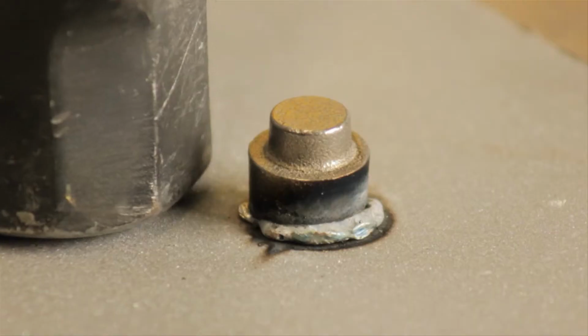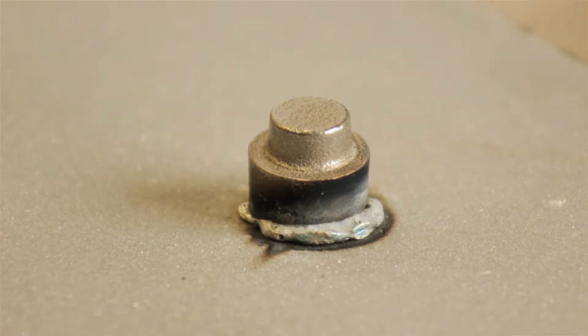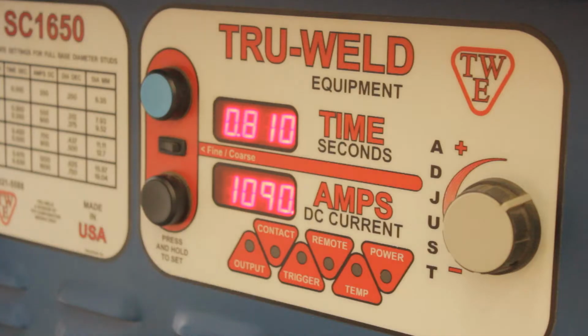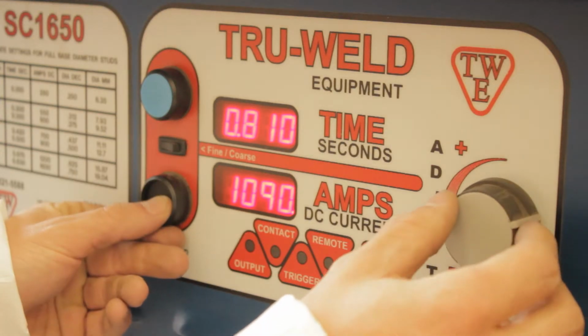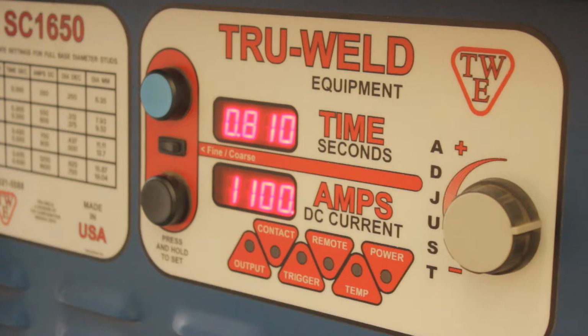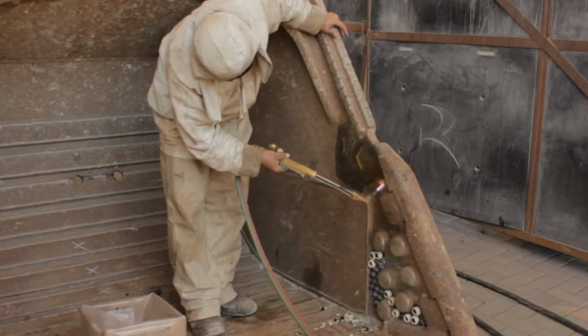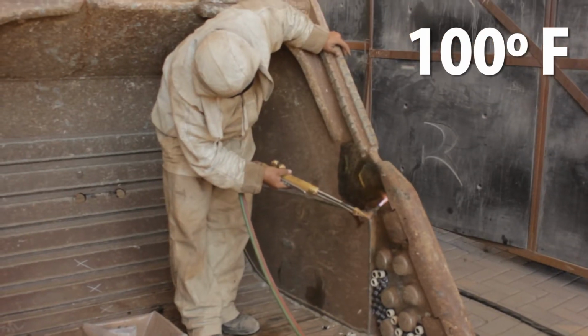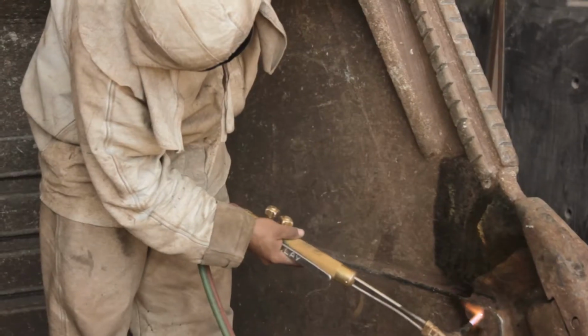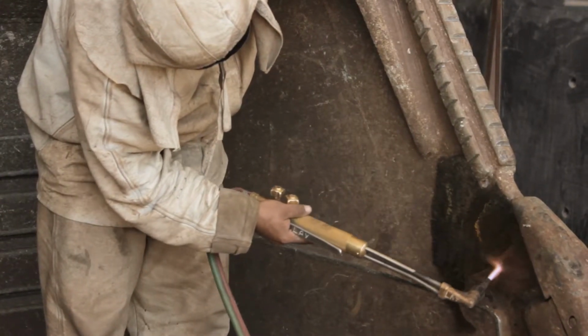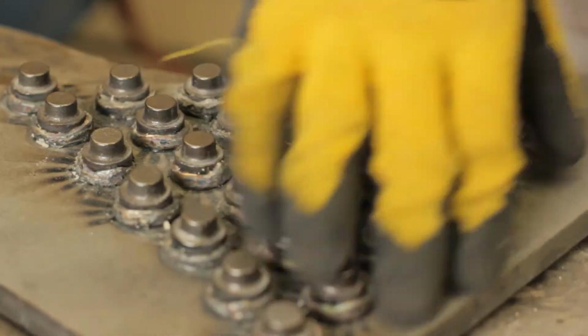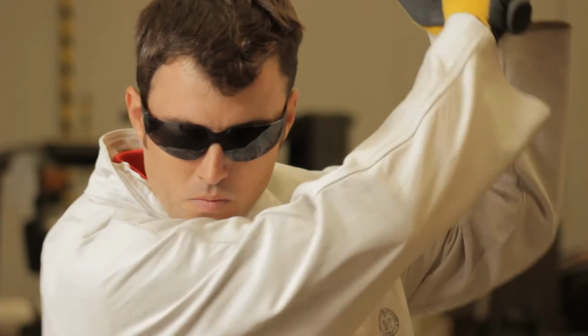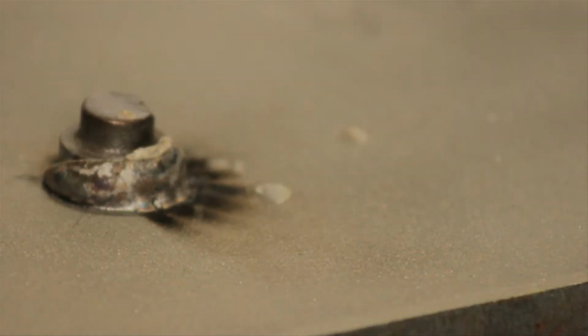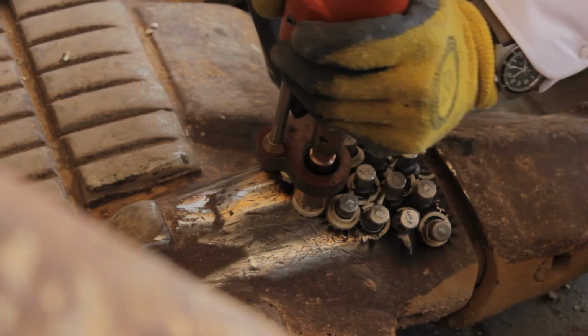If the stud comes out of the base material, it indicates a cold weld. You will need to increase the time or amperage until good quality welds are achieved. A preheat of 100 degrees Fahrenheit or 38 degrees Celsius may be necessary due to work-hardened base material. Due to the hardness of TuffStudds, it is possible to fracture a TuffStud with enough force applied. This is the nature of very hard materials and should not be a concern.